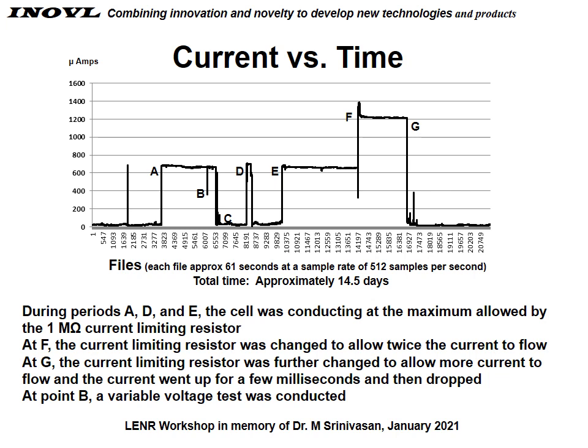Here's an example of what happened during those tests when we were conducting the experiments. You see, we'd start out and they were all different. Every one was different, but this one started out very low current for a few days. One spike that perhaps lasted a few milliseconds or maybe even a minute. And then at point A, it jumped up to close to 700 microamps of current. That continued. At point B, we did a load test. I'll say a little more about that later. At point C, for some unknown reason, it dropped down. At point D, it went back up and then dropped down.